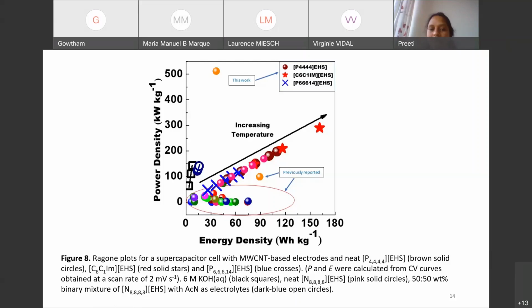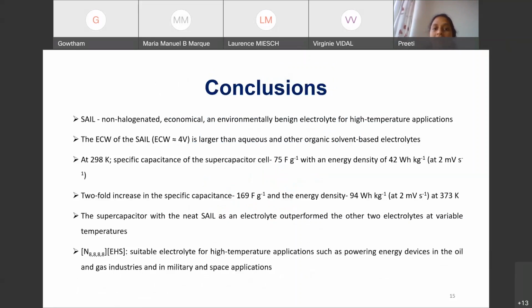Out of all these studies, we have come to the conclusion that these surface active ionic liquids are non-halogenated, economical, and environmentally benign electrolytes for high temperature applications. As we have seen, at room temperature we get less specific capacitance, but when we move towards 60, 80, and 100 degrees centigrade, these ionic liquids outperform the other electrolytes. Another important factor is the larger electrochemical window. We can use up to 6 volt, but due to polarization we have used 4 volts, which is very large as compared to aqueous and other organic solvent-based electrolytes.